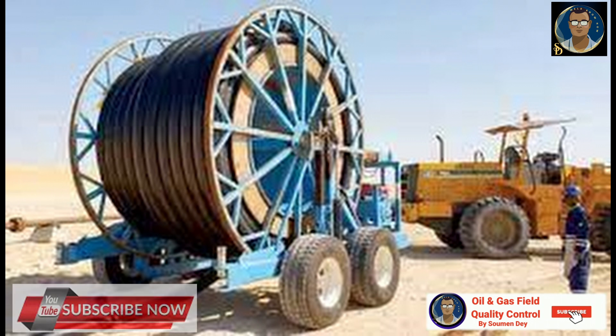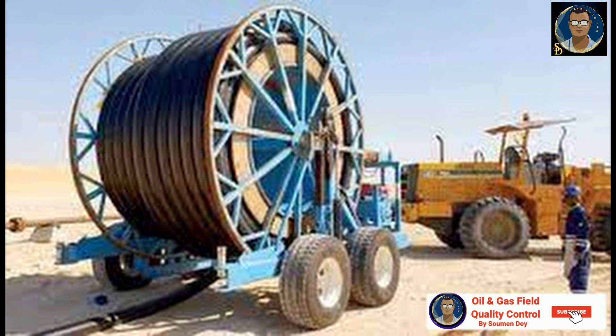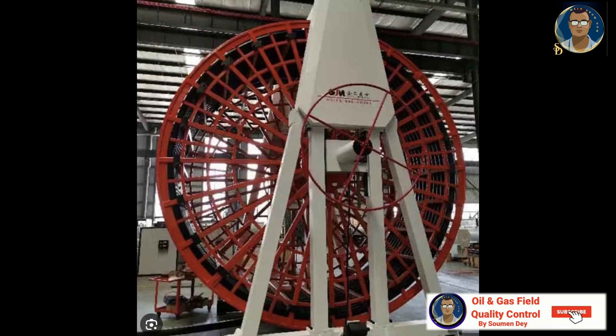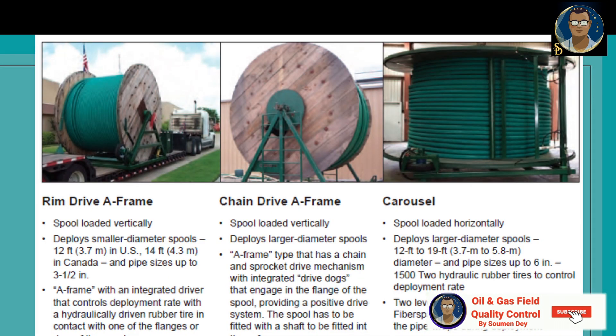The core diameters of RTP spools are selected to ensure that bending strains are within allowable limits. Hydro testing of RTP line pipe is carried out on specially reinforced spools at manufacturing locations. RTP line pipe must never be subjected to pressure on a shipping spool. RTP has designed and manufactured spooling equipment suitable for deploying and re-spooling of RTP line pipe. Approved equipment must be used for these operations. RTP can be spooled using three spooling frames, all of which require a hydraulic power assembly for operation of the hydraulic drive control motors and level wind arms on the carousel frame.